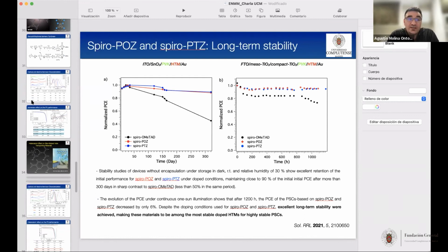We never tried that, but there are a few groups not using just the TPA, just the triphenylamine. I mean, just using a small donor-acceptor system, a TPA with a carboxylic group, the kind of molecule that you use in dye-sensitized cells, and it had very good performance, around 17-18%.